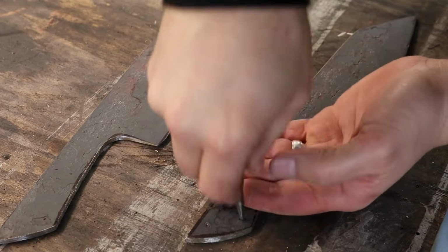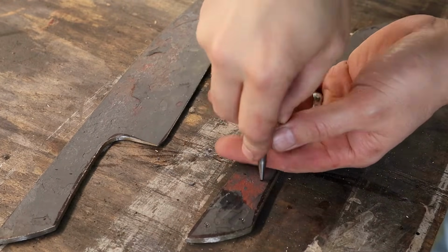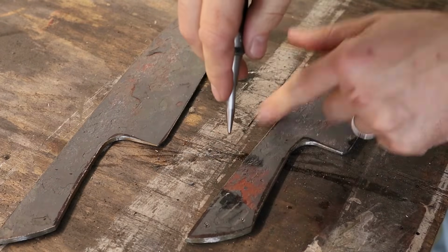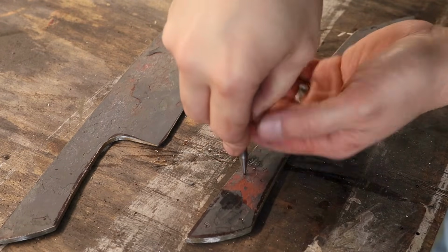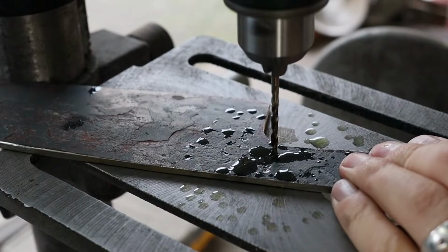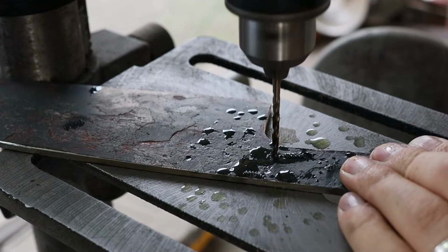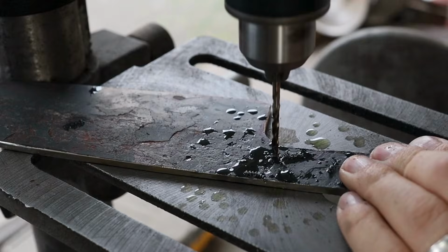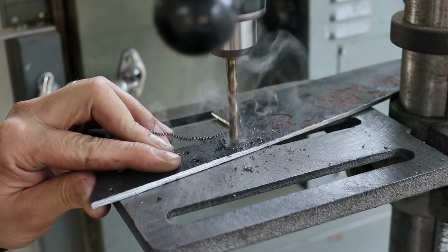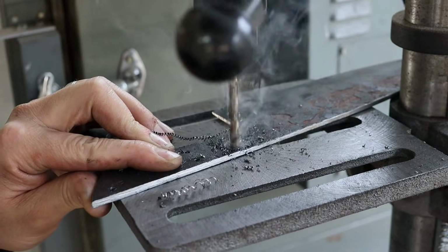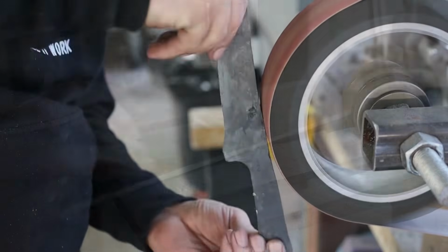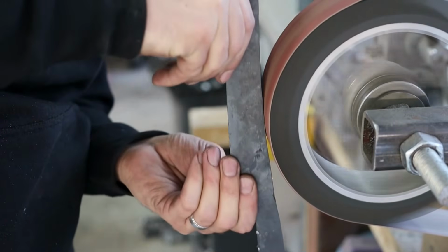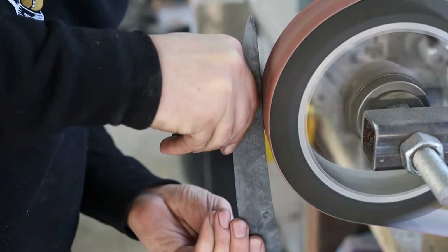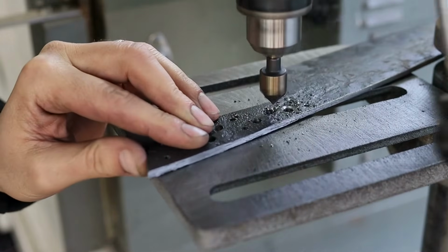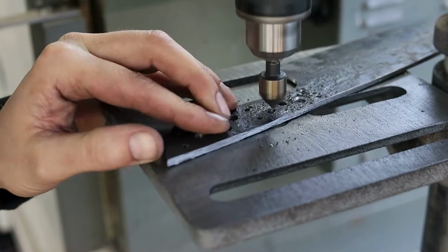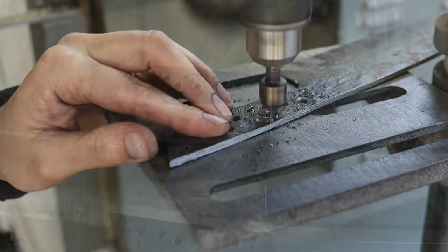Now that the blades are profiled, I'm going to mark out some holes for handle pins. In addition to the 3mm holes for the pins, I'm also going to add several larger holes for weight reduction and also to allow the epoxy a channel to bond through the tang and to the scale on the other side. I chamfer all the holes to reduce the risk of a hard 90-degree edge causing a crack during the quench.